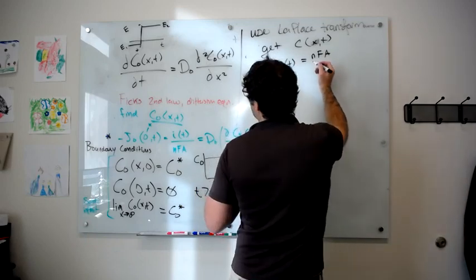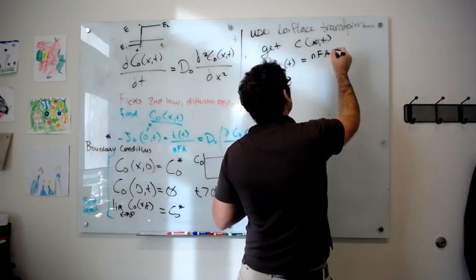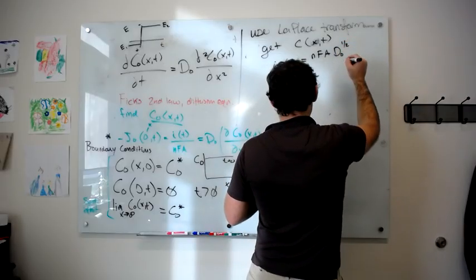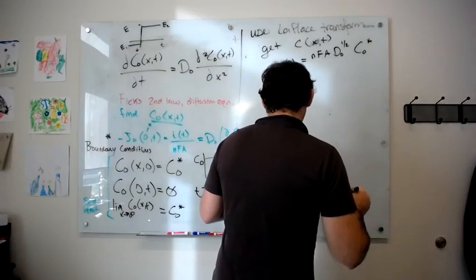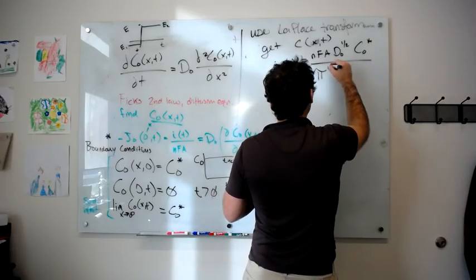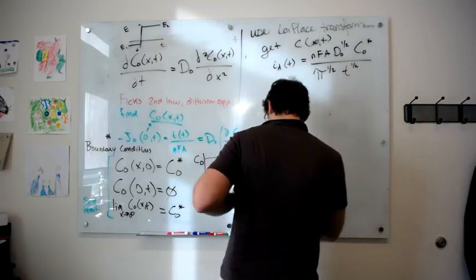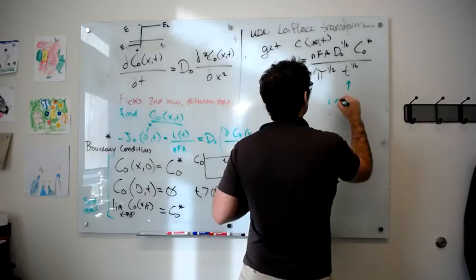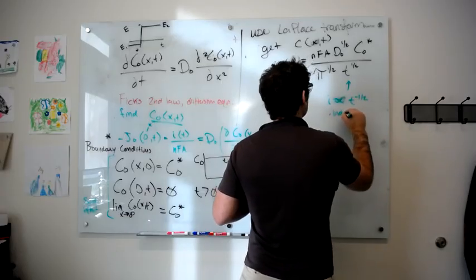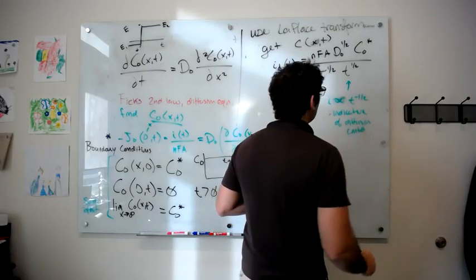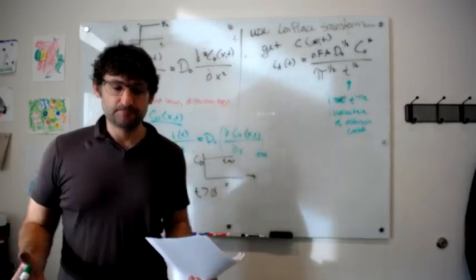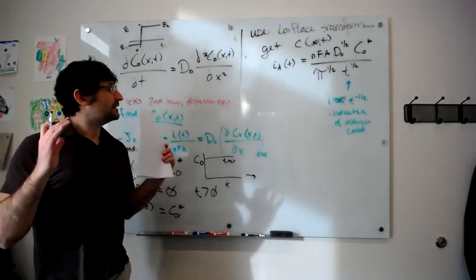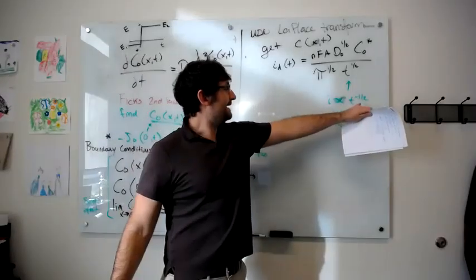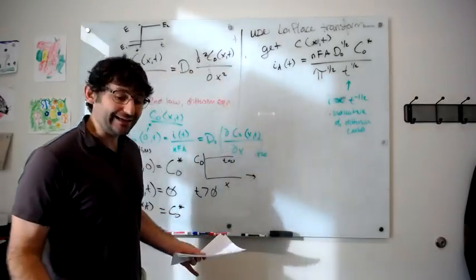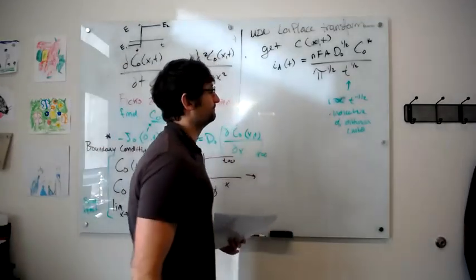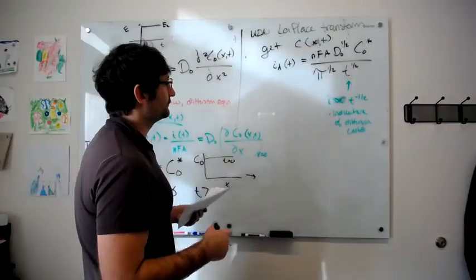where n is the number of electrons in the electrochemical reduction reaction, O plus n electrons goes to R, F is Faraday's constant, A is the area of the electrode, D to the 1/2 is the diffusion coefficient of the species, then the bulk concentration, it's linear in bulk concentration, over pi to the 1/2 times t to the 1/2. And you'll notice i is proportional to t to the negative 1/2, and this is indicative of diffusion control. So whenever you do any type of experiment, and your result is that the response decays as t to the negative 1/2, that tells you that likely whatever controls that response is controlled by diffusion. And that's because it takes longer and longer for things to diffuse from further and further away.